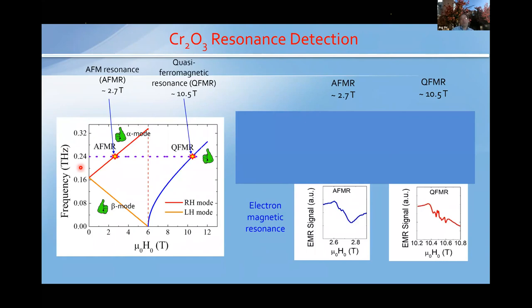Okay, as I mentioned, we expect to see these two resonances. So we use the conventional detection based on bolometry in this setup. By sweeping the field to the antiferromagnetic resonance, located at about 2.7, we do see some wiggle, some feature here. Off resonance, we see pretty much a flat line. The same is true for the quasi-ferromagnetic resonance: we see some wiggles here, something different from the off resonance feature.